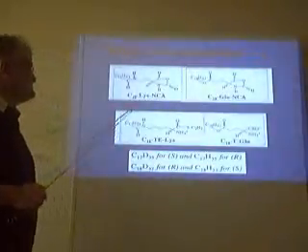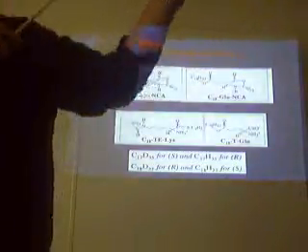We went to lysine. The reason why lysine undergoes spontaneous resolution is that you have this amide bond, which forms a hydrogen bond, and the hydrogen bond defines a translation axis, which is an axis of chirality. It forces the molecules to crystallize along one axis of chirality, and then the CONH defines another axis of chirality. So you have two hydrogen bonds, which define two translation axes, and force this molecule to undergo spontaneous resolution.